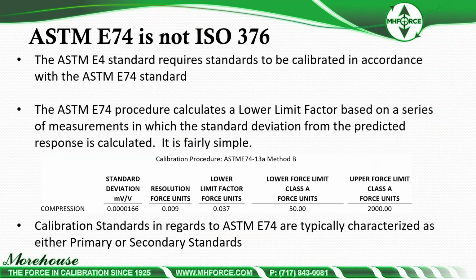What is in ASTM E74 is a procedure that calculates the lower limit factor based on a series of measurements in which the standard deviation from the predicted response is calculated. It's fairly simple. We're going to calculate the standard deviation. We're going to rotate the instrument like we did in ISO. That's 0, 120, and 240 is recommended. We report the resolution, the lower limit factor, and then we assign a range. In this situation, it's just class A or double A, depending on what's going on.